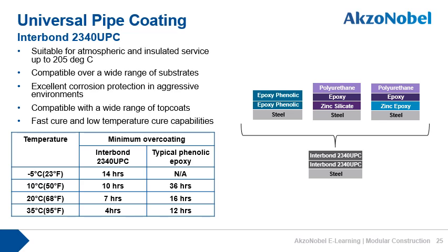Another important advantage is that Interbond 2340 UPC shows excellent corrosion protection at ambient conditions, which is something that phenolic epoxies fall short of. This could be vitally important in large modular construction projects where piping equipment can lie around in the fabrication yard for months or even years before it is shipped to the site and installed. We've seen multiple cases where the phenolic epoxies have started to break down even before installation, and this obviously causes a huge amount of not only costly rework but potential delays to the project.